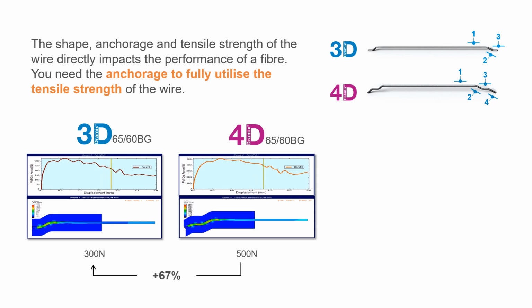If you look at the 3D 6560 BG fibre, on the other hand, we're using a lower tensile strength wire because it takes less force to pull the fibre through. If we used a high tensile strength wire, that tensile strength would purely be wasted because the fibres would pull through, not utilizing the full tensile strength of that wire. There's about a 67% increase in pull-out force between the 3D and 4D 6560 fibres.